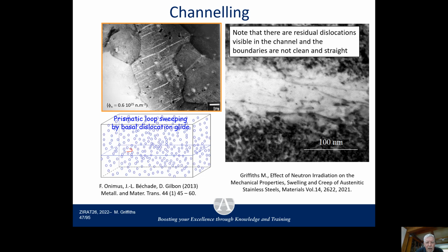And when they do that, they climb. They actually move off their slip plane. It's like cross slip, if you like. And that creates a thicker, broader volume layer of material, which is essentially reduced in dislocation, softened.